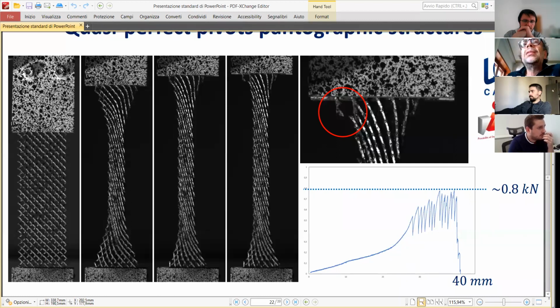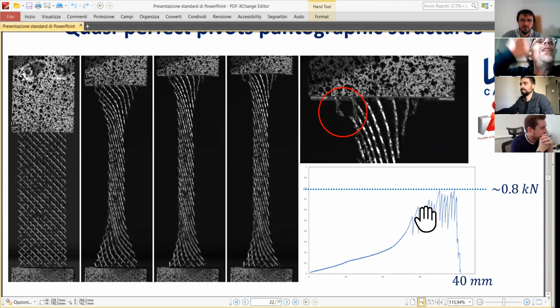This is displacement, exerted force in the bias test, okay? Consider that at the maximum, this specimen, which is 3 centimeters times 9 centimeters, can exert 0.8 kilonewton, a lot, okay? And consider that a specimen which is 9 centimeters long can elongate 25 millimeters before going out of the elastic regime. Okay, what happens in this point? A first pivot is broken. Okay, then you have a sequence of ruptures when other pivots are broken without failure.